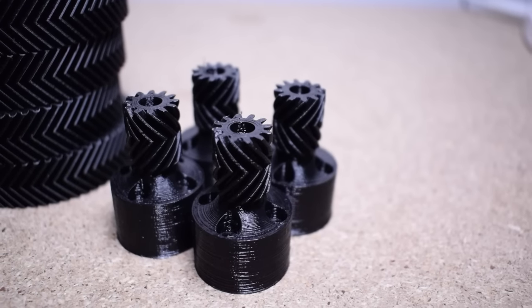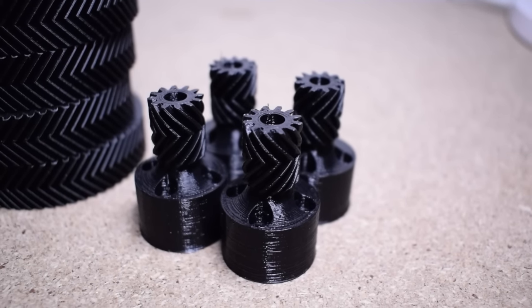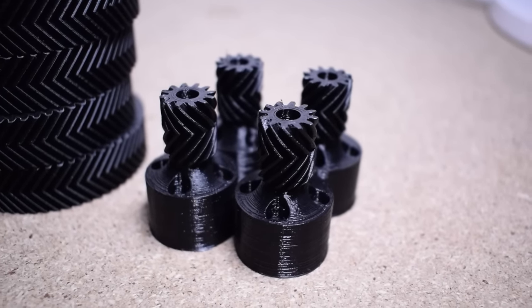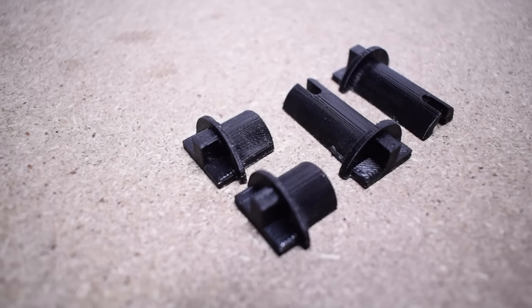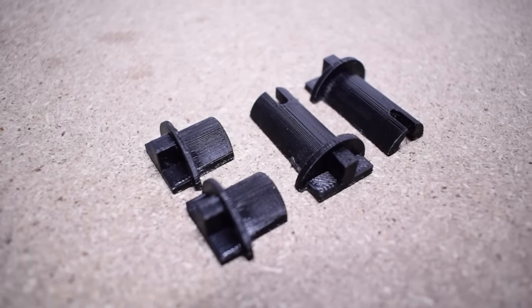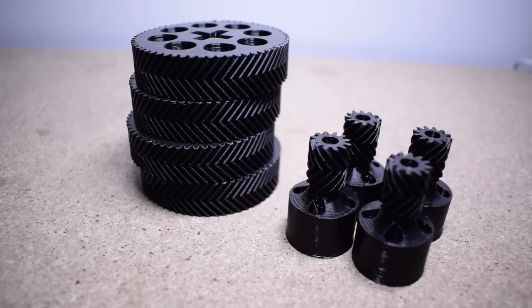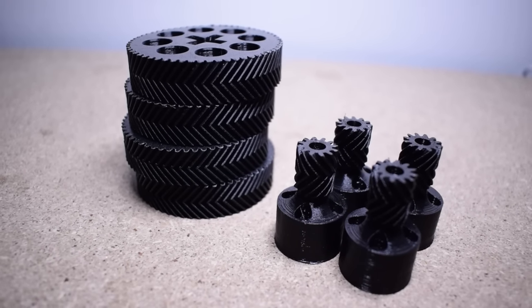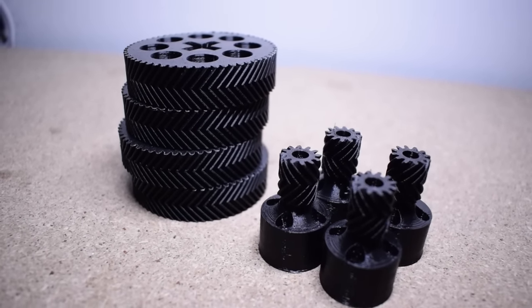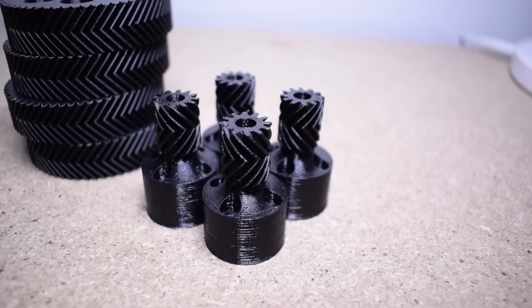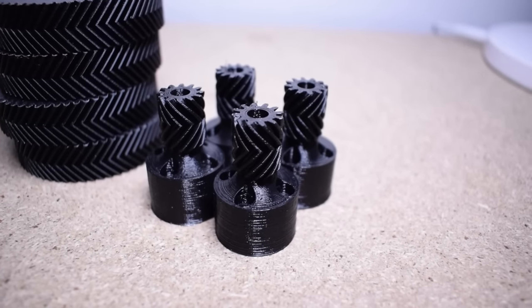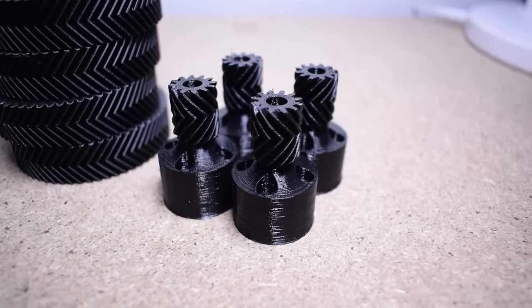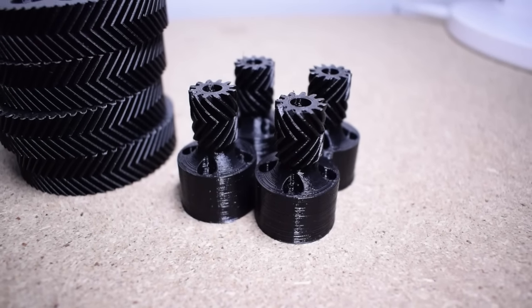Here are my final spur and pinion gears. I recommend that you print any smaller parts such as pinions or axles at 100% infill because it's going to give you the best durability. Given that the spur gear is larger and I'm mindful of weight reduction, I decided to print those between 20 and 50% infill. The outer perimeter of the print where the teeth are is quite thick anyway and this is another setting that you can play around with in your slicer.